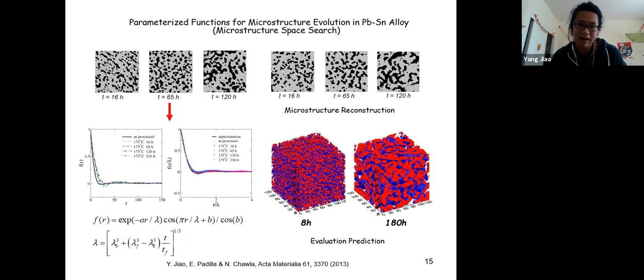And the size of this black phase clearly determines the mechanical properties. If you drop your cell phone, you don't want these interconnects to be broken, you want them to be stable, right? So you can still use a cell phone. So the size of this black phase basically determines how brittle this interconnect is.